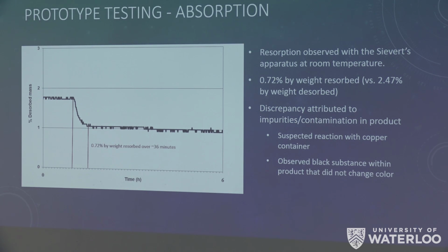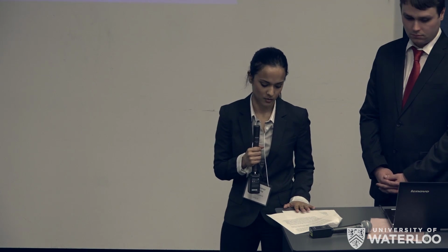We have hypothesized that this is because there is such a high concentration of impurities within our crystal that there may be some alternative reactions going on that may be binding or releasing oxygen that we don't know. Further characterization testing, such as FTIR, will be a next step for us to determine what kind of impurities are in there and why our oxygen has not been reabsorbed as much as we thought it would be. It is also noted that there was no color change between the two crystals as seen in literature, and we also attributed this to some impurities or imperfections in our synthesis technique that may be hammered out in another run.